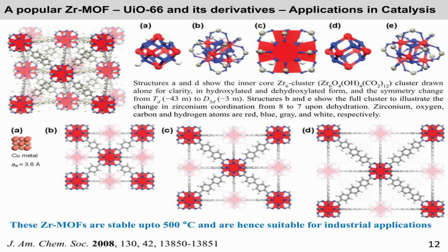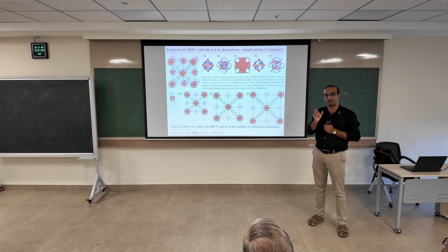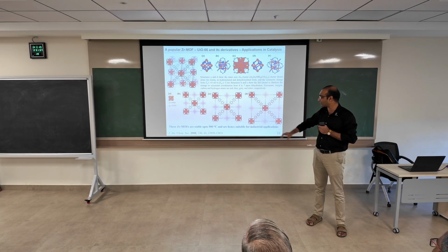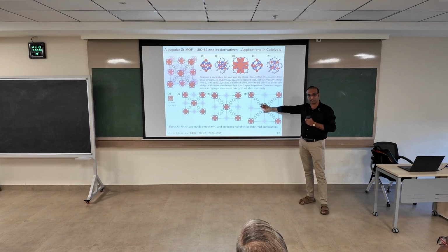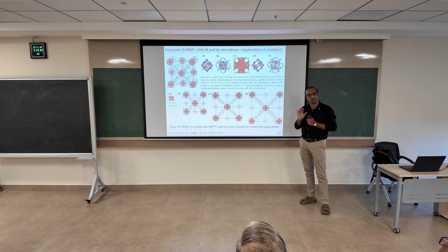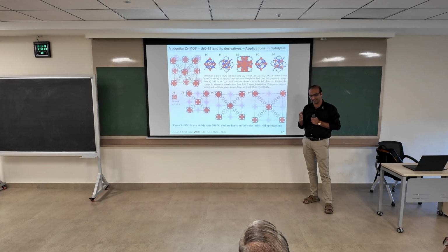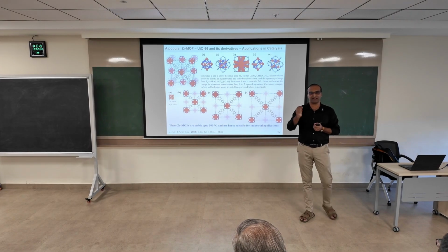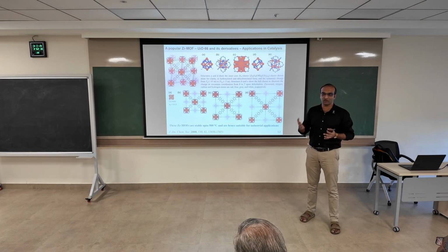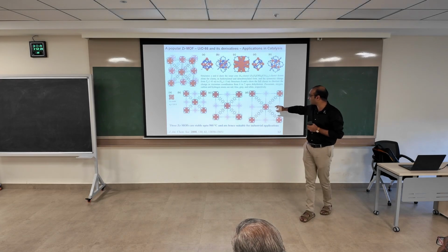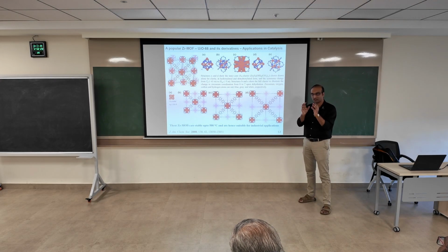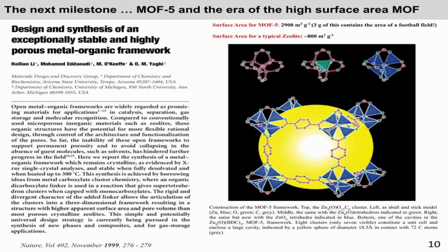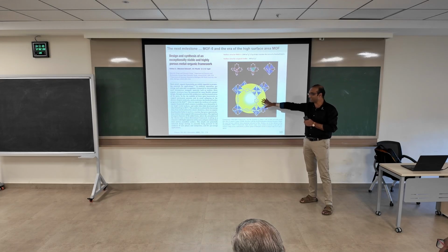This is very good for catalysis. Basically, you can tune the linker and even the functionalization on the linker to have it capture CO2 more, or capture platinum nanoparticles. We use it to capture nanoparticles and make very high loadings of nanoparticles and increase their surface area. Typically, most of the supports in catalysis, in any industry, they'll take silica, which is very easily available, right? Porous silica is very easily available. And when you put metal, you can at most put like 1% metal loading, and then you have to use a large amount of the catalyst. In these kinds of MOFs, because of this contained environment, you have these pores; each of these MOFs is one unit, like an extended network where you have all these small holes of a certain size. You can design the size you want. You can control it, and making these MOFs is not very hard.